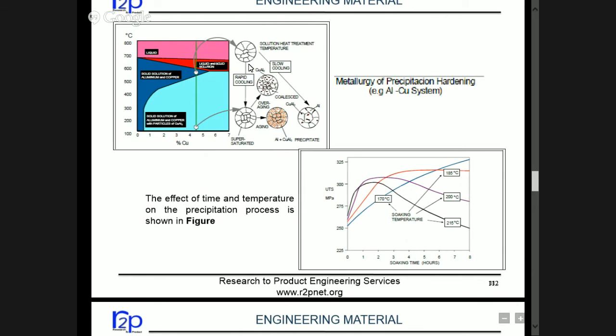So that all the alloying elements get into the solution form, right? And then it's rapidly cooled so that they are not able to go back into that form. They are retained on the grain boundaries. The copper or the silicon settle on the grain boundary, and then we do the overaging. Overaging meaning we again heat to around 180 to 200 degrees centigrade, retain it there for 2-3 hours, and then let it cool. So by this whole process, we are able to almost double the tensile properties.